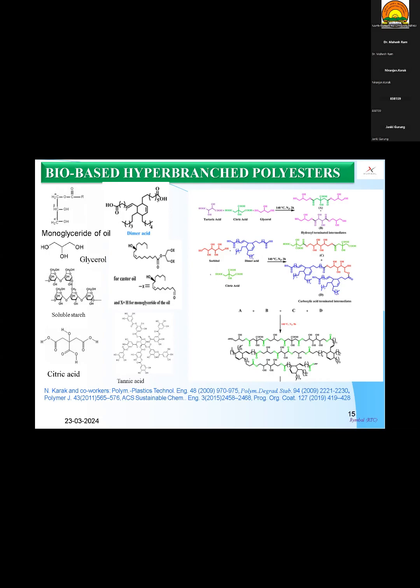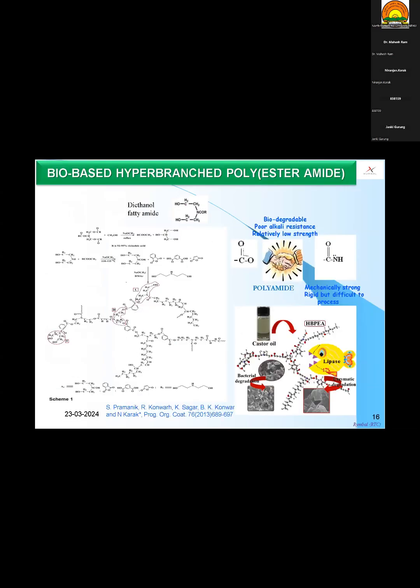However, you have to remember that polyester, as the ester linkages are vulnerable to alkali, when you need alkali resistance, these are not the polymers. Hence, to improve its performance, we have given a marriage between the ester group to get the flexibility and amide, because the amide group has very strong alkali resistance, and you will get a tough material. So if you can give a suitable marriage between the ester and amide to produce a polyester amide system, then you will not only get the flexibility, toughness, alkali resistance, but also it will provide biodegradability.